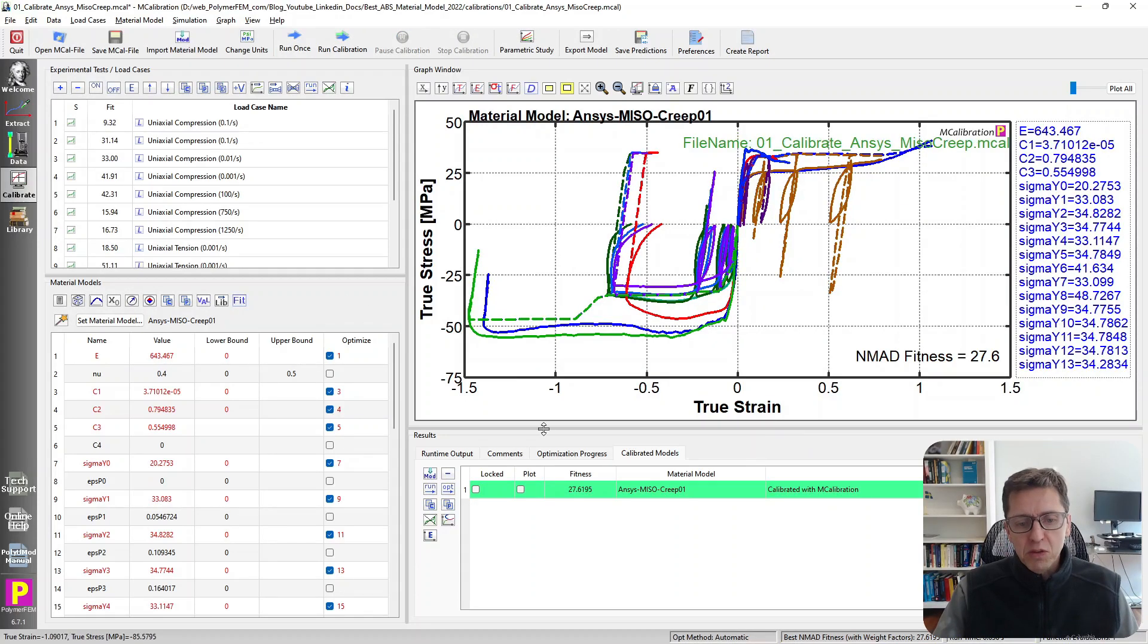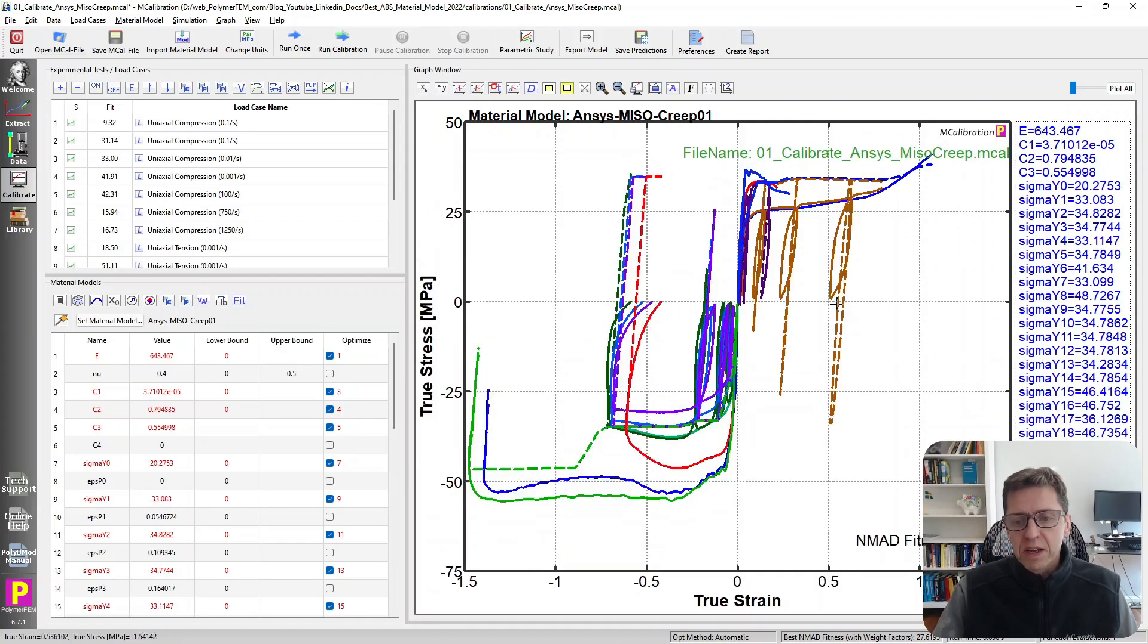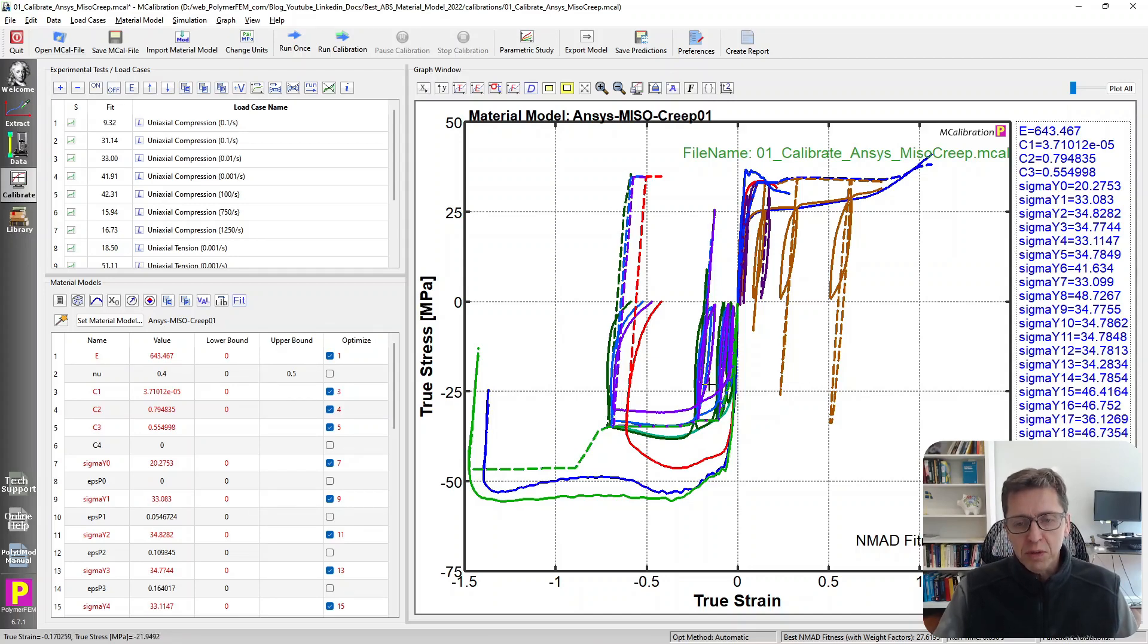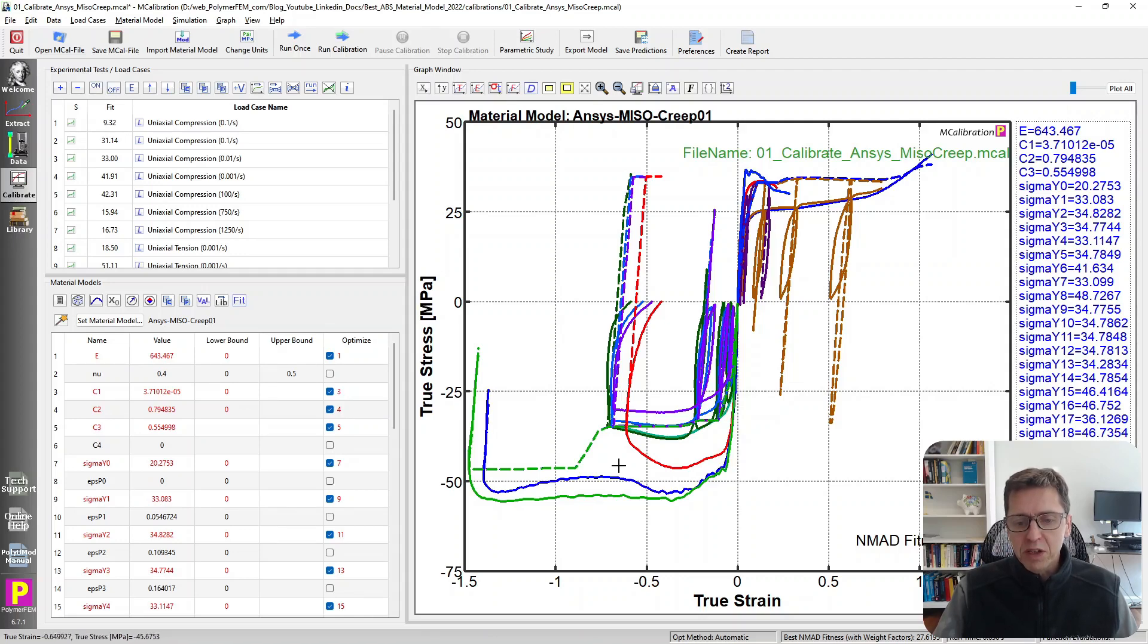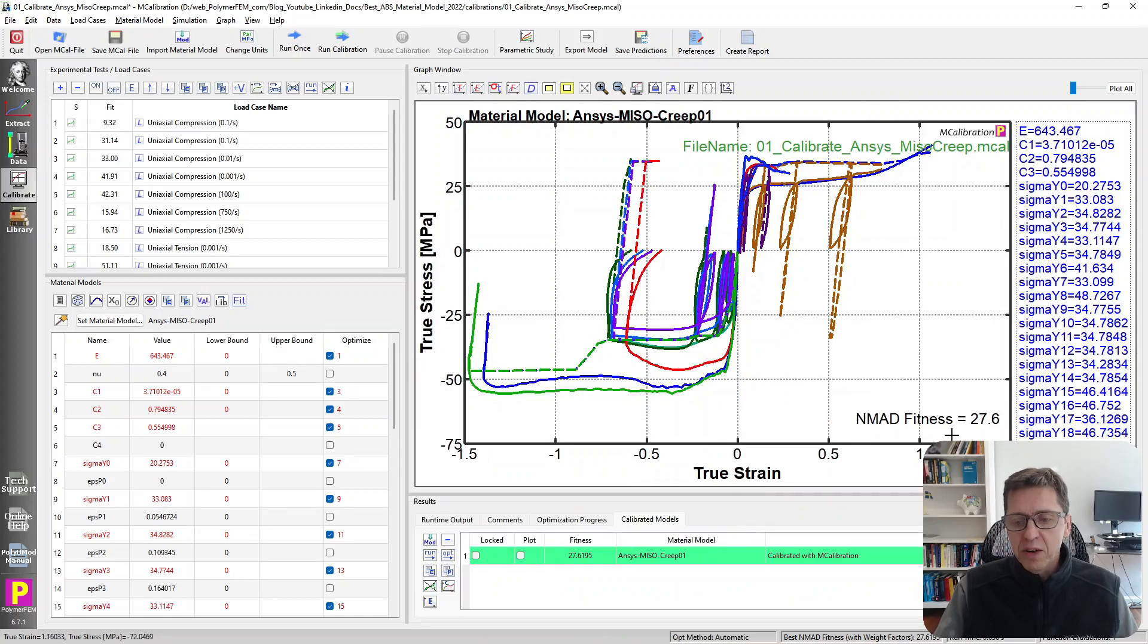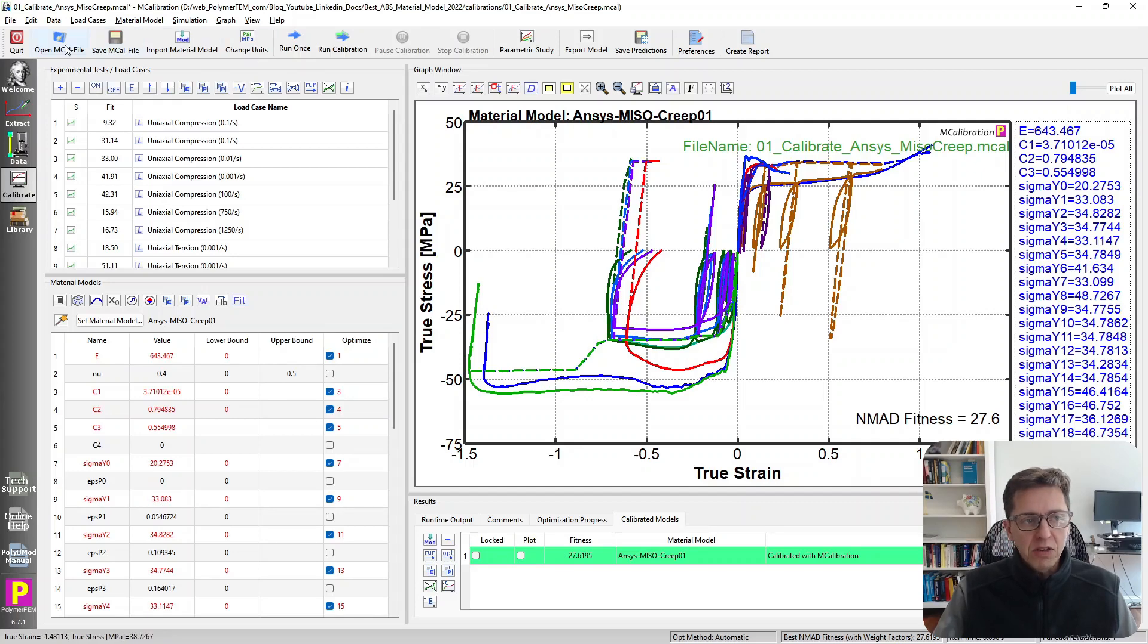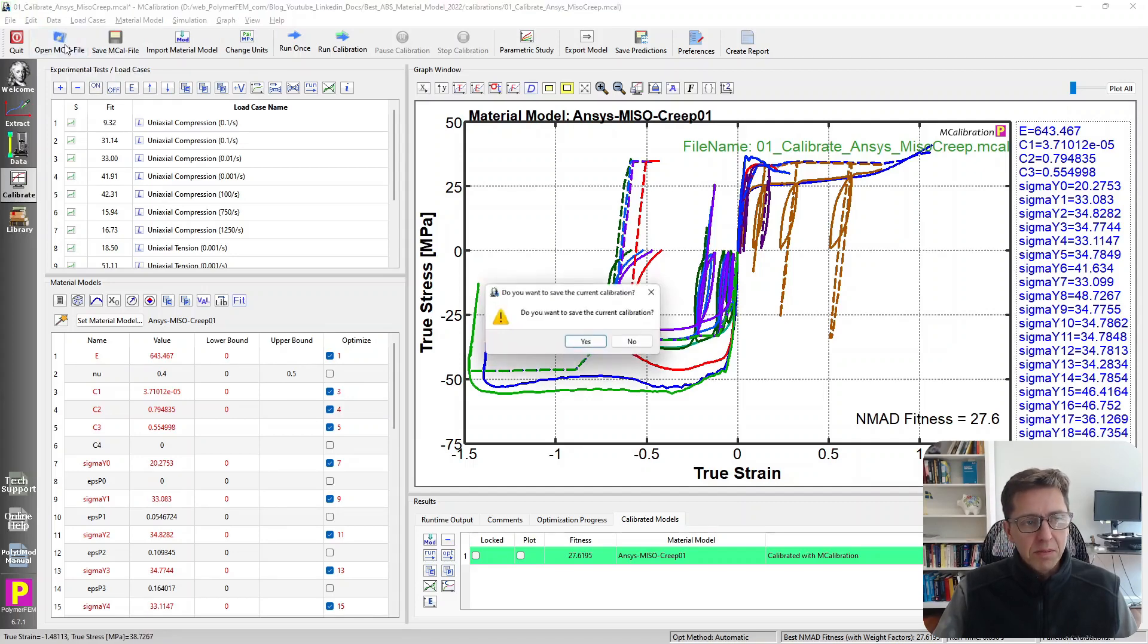If I run this once, we can see that the unloading predictions here are very linear, as one would expect for an isotropic hardening plasticity model, not like what happens in the experiments. The predictions are also pretty poor between tension and compression, as we would expect. The error is about 27-28 percent. Not a model that I recommend for ABS. Let's try something else.